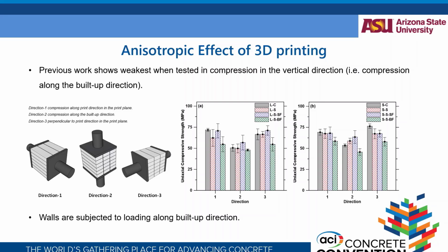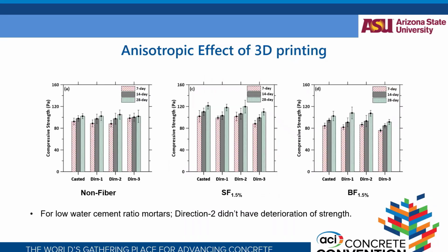This has been consistent over the normal strength mix. This is the high water cement ratio mix again. Now coming to the low water cement ratio mix, this has SP. So when you are extruding it through the auger, the vibration and movement make it more flowable. What we observed is that direction 2 does not have that effect; the strength reduction is not there. All the experiments are based on a layer height of 10.